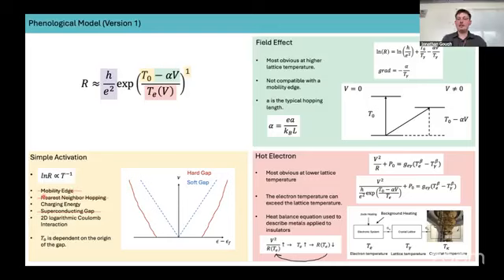For example, nearest neighbor hopping, where you have this fixed range hopping distance. Things like a charging energy can also lead to this effect. A superconducting gap. Indium antimonide itself is not superconducting. However, indium is, which may be relevant for some of our observations. And obviously, there's more complex explanations, something like this 2D logarithmic Coulomb interaction.